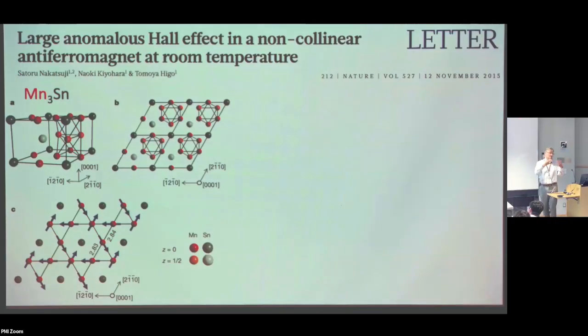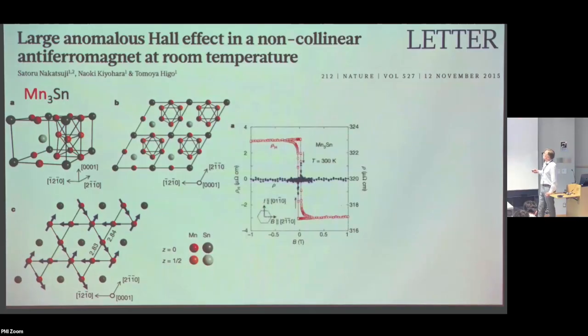Now this material, that was Satoru Nakatsuji who discovered it, but what's interesting is that it has an anomalous Hall effect. So even in the absence of an applied field, if you train the sample, you have to initially apply a field, then you can withdraw the field, and then you'll actually see a Hall effect, and you can switch the sign of it as well. It's a very strong Hall effect, as strong as really an iron. So this is really a new kind of addition to it. And so this is the effect.